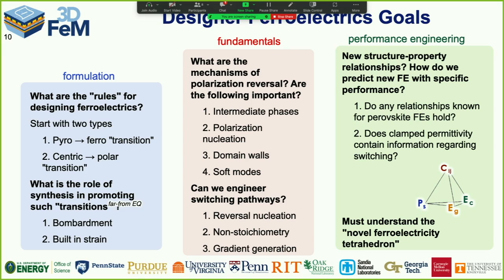So how would you go about designing a material for a ferroelectric application? Well, there's a couple of possibilities. We have lots of materials which are polar, but which we don't know how to switch. So the polarization, we grow it in that orientation, but we don't necessarily know how to switch it. And if you can't switch it, it's not ferroelectric. So can we start with a material which is polar and engineer the switching barrier? Alternatively, can we start with a material that's not ferroelectric at all and start shoving atoms around in the solid to induce a polarization and switch it that way?